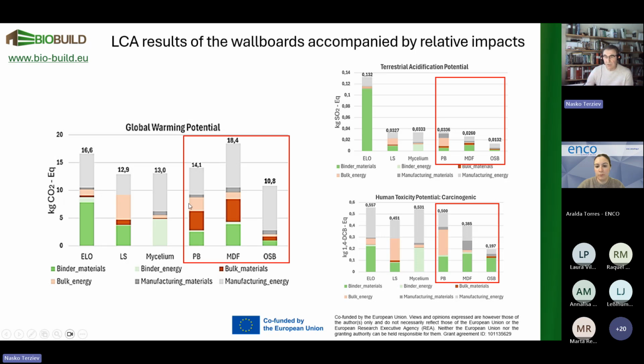They are not higher than, for example, particle or medium density fiberboards. They are somewhat lower. The same can be seen, for example, for terrestrial acidification potential. It is more or less equivalent to that of the particle boards. For human toxicity, we have somewhat lower toxicity, for example, in the lignosulfonate binder compared to particle or medium density fiberboards. So the project is going on, and it is approaching the most exciting phase when the materials will be produced, and we start our practical testing maybe in the middle of the year. So thank you very much.